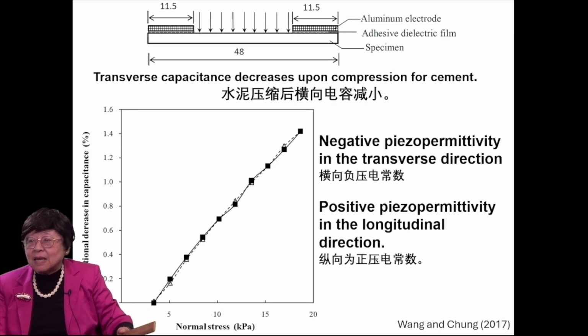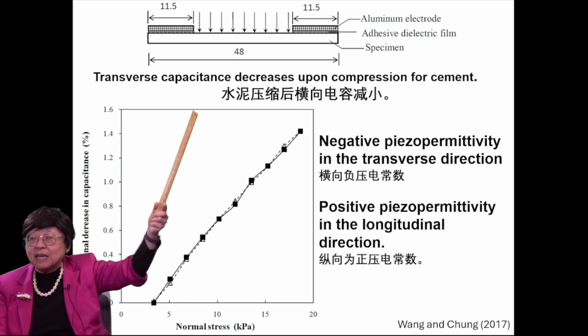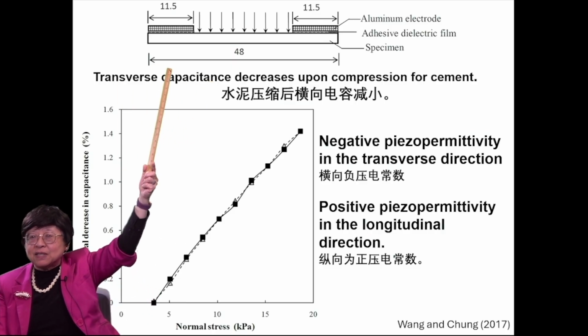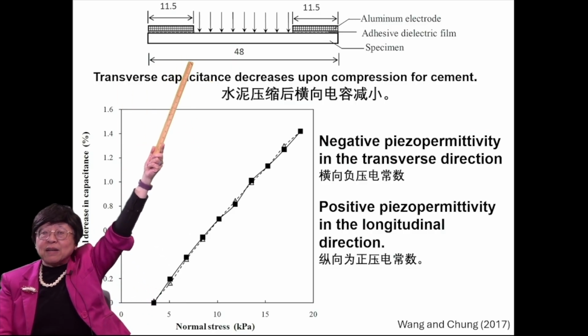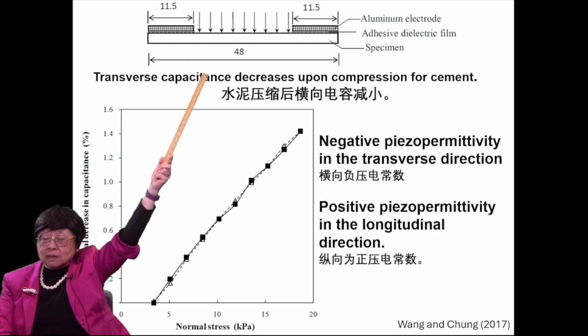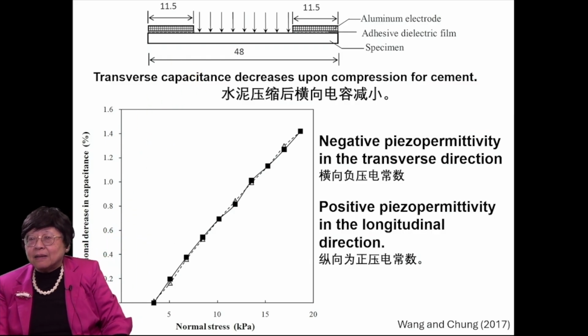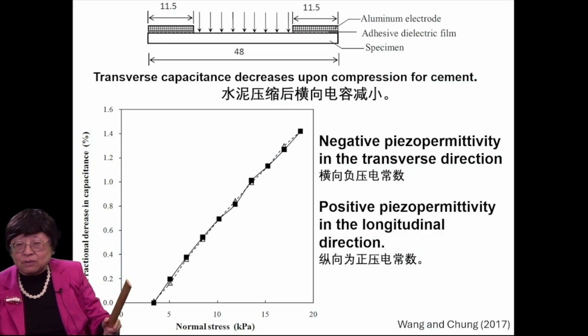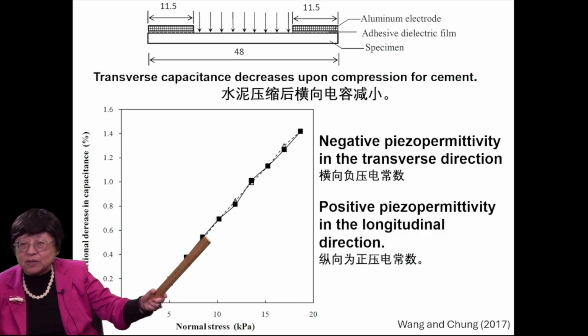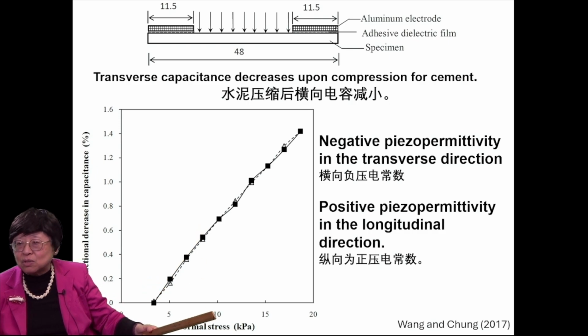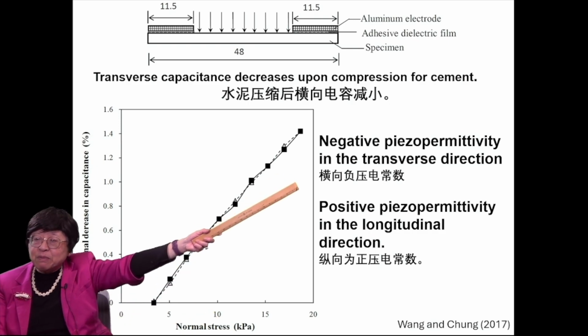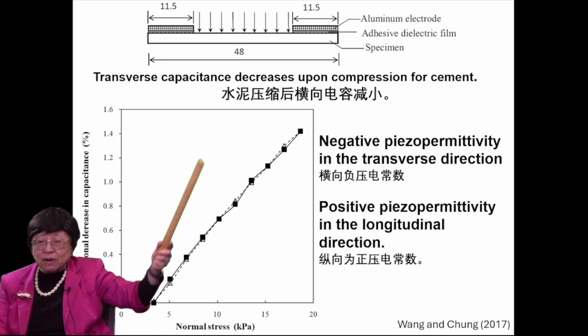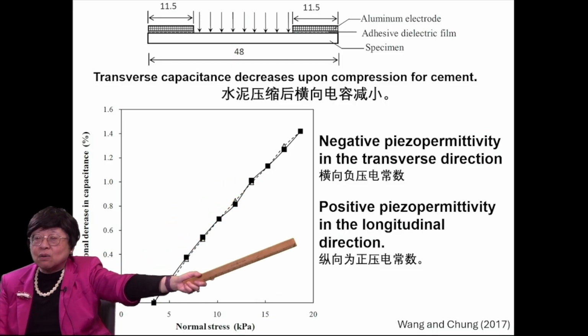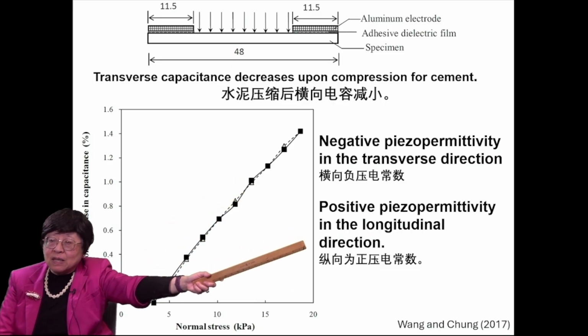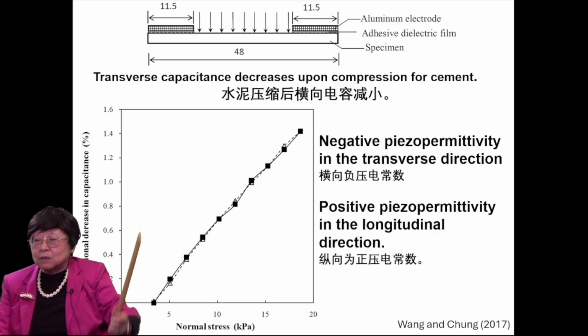This illustrates negative piezopermittivity in the transverse direction of cement when the compression is vertical. So horizontal is transverse, and the horizontal capacitance decreases. This is the fractional decrease in that horizontal or transverse capacitance due to the normal stress. So it's negative piezopermittivity in the transverse direction as shown, and not shown is the positive piezopermittivity in the longitudinal or vertical direction.